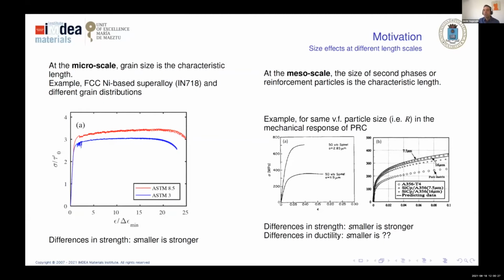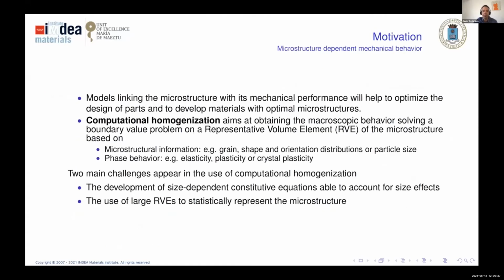So in this case, the smaller the reinforcement particle, the stronger the response. And this effect is also observed in ductility. Ductility is also affected by the size of the particles. Okay, so we want to study that, and we want models that are able to link this microstructure, including size effect, with a macroscopic response, and computational homogenization is probably the best option.